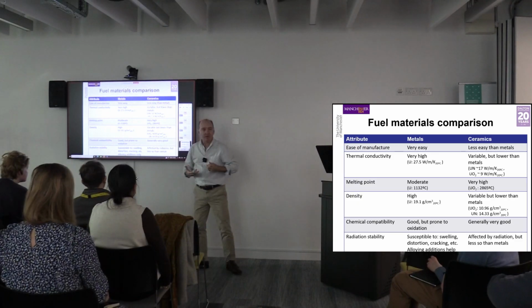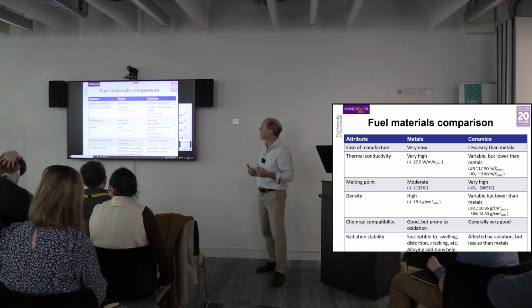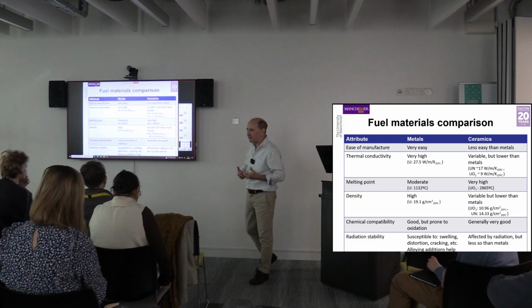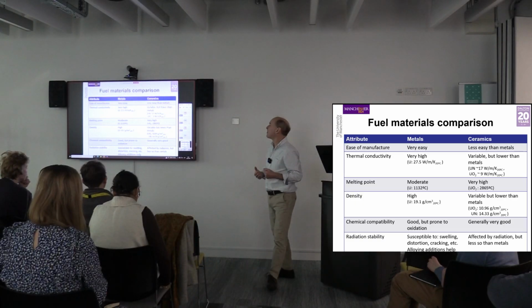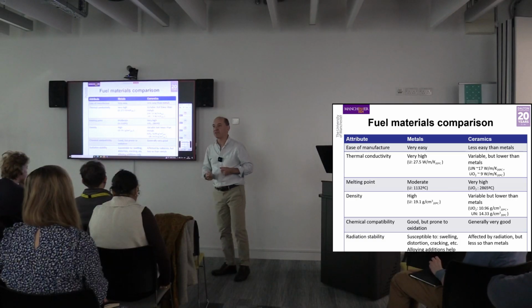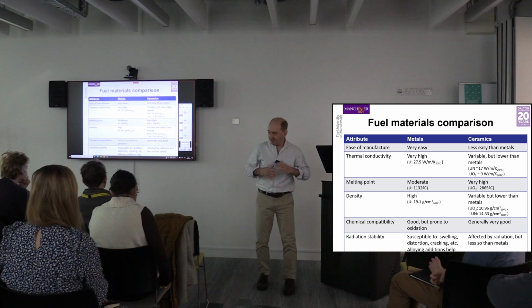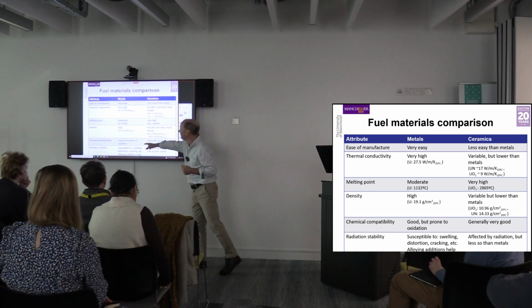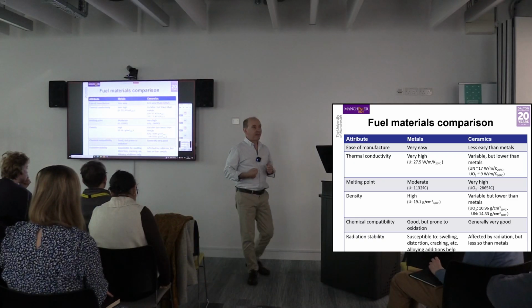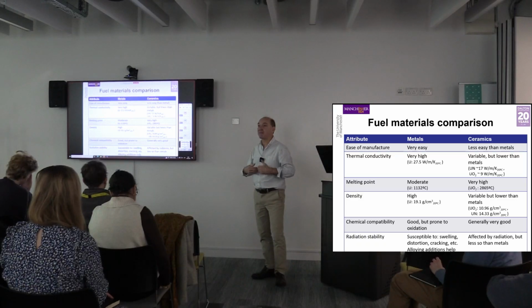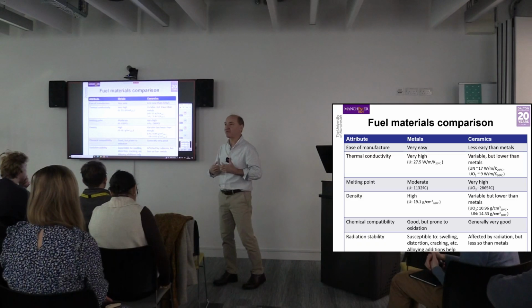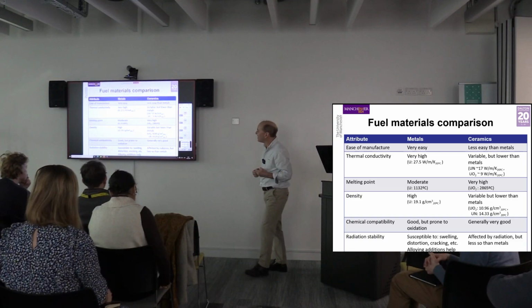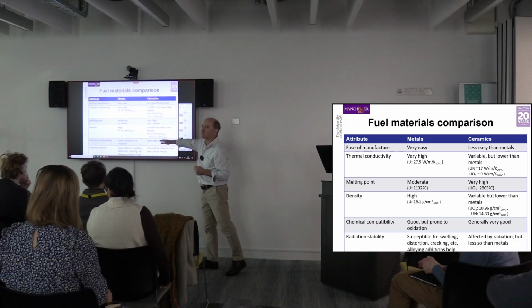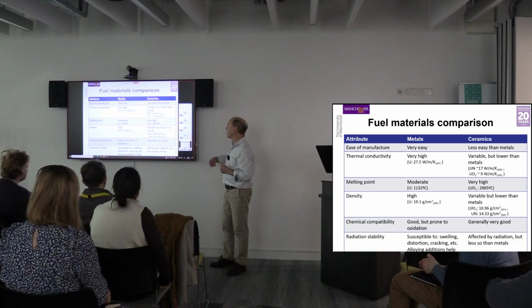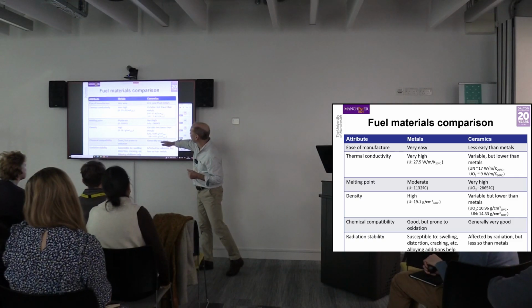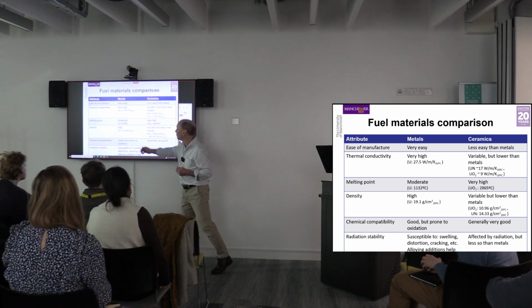Chemical compatibility, so in other words, might it start reacting with the substances that it comes into contact with? With a metal, yeah, generally, they are prone to oxidation. I'm definitely no chemist, but one bit of chemistry I do know is that pretty much everything wants to be an oxide, sooner or later. And metals are no different. They are particularly fond of becoming oxides. And even when they are oxides, it's reasonably easy to persuade them to become higher oxides. So UO2 isn't the end of the story. UO2 can be oxidized to U3O8 or UO3. Generally, though, that happens less in ceramics. Once something is already an oxide, it's more difficult to persuade it to become a higher oxide. So generally speaking, ceramics are much more compatible chemically with things, metals more prone to react.